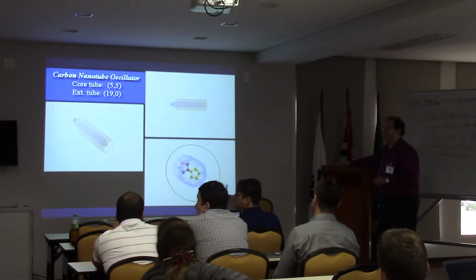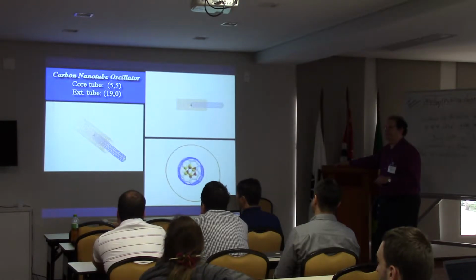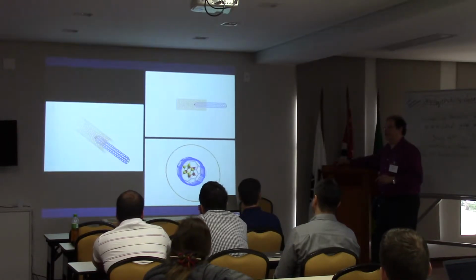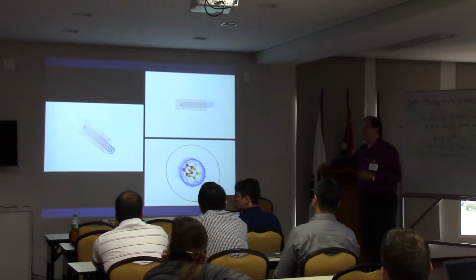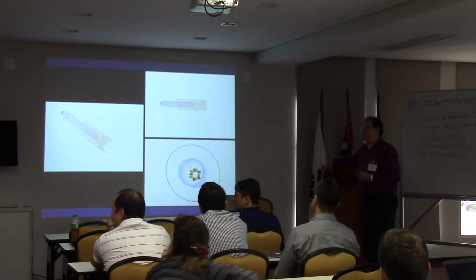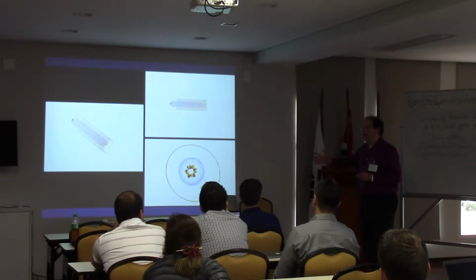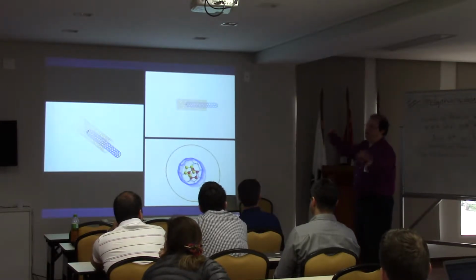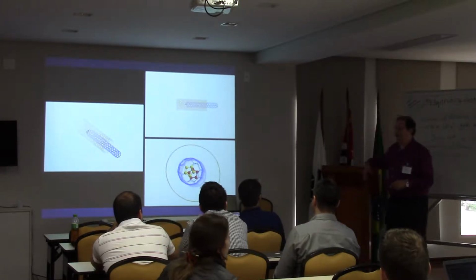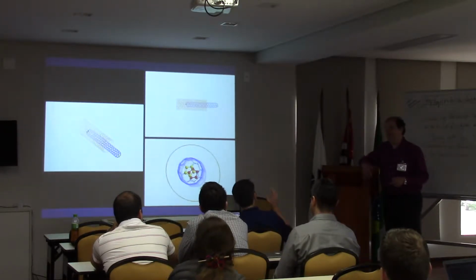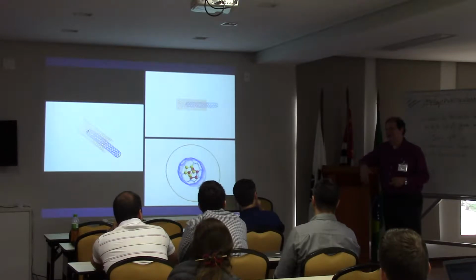Please. So the outer one is constrained? It's frozen, just to mimic the experimental condition, when you have many outer layers. But in principle, you can have both tubes free to relax. That will compromise the oscillation a little, but it still works.